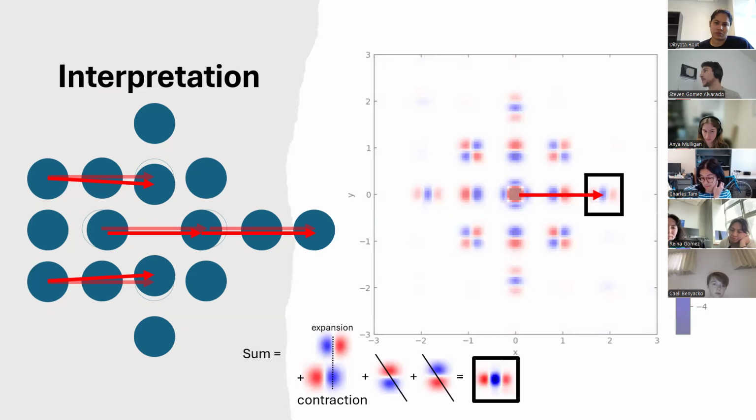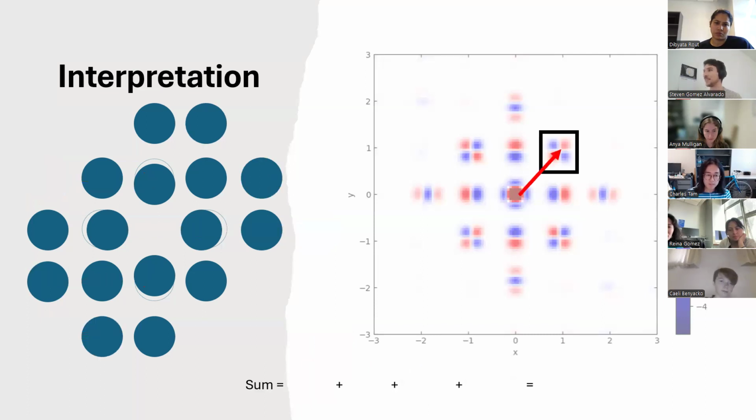All right, so now this nightmarish looking thing that exists diagonally, right? It's like quadrupole four-leaf clover looking business. This one's a little bit more of a nightmare to interpret. So again, we're going to look at correlations that are 1 unit cell to the right and 1 unit cell up. So the first one I can think of is that one, where there's a change such that both of these vectors, before and after the distortion, they've picked up some translation to the right. Okay, so they're both going to constructively interfere with each other.